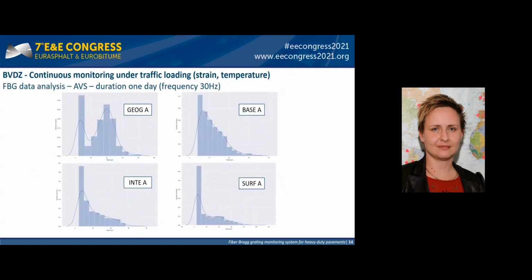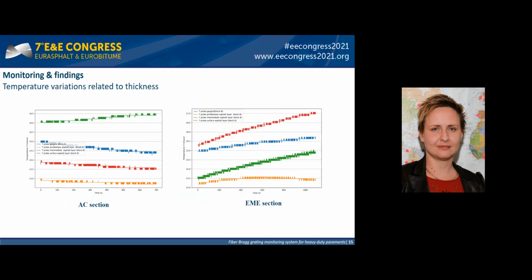Performing continuous monitoring of the pavement, there is a possibility to have an overview of the applied strain values and their intensity over time, which normally have to be below 50 microstrain. And here you might clearly see that some of the asphalt layers are overloaded. Performing continuous monitoring of the pavement, there is also a possibility to see the variation of the temperature in different asphalt layers and asphalt types.